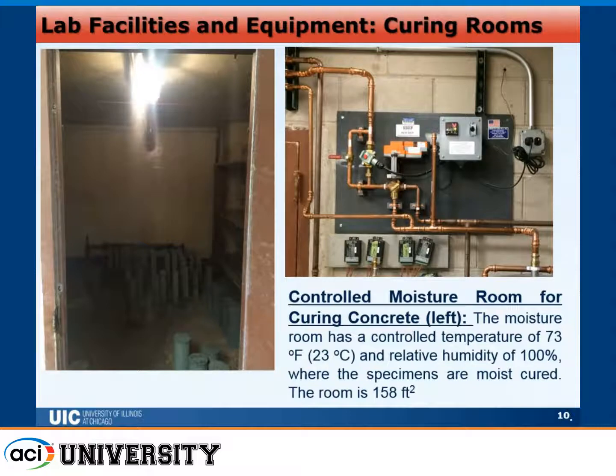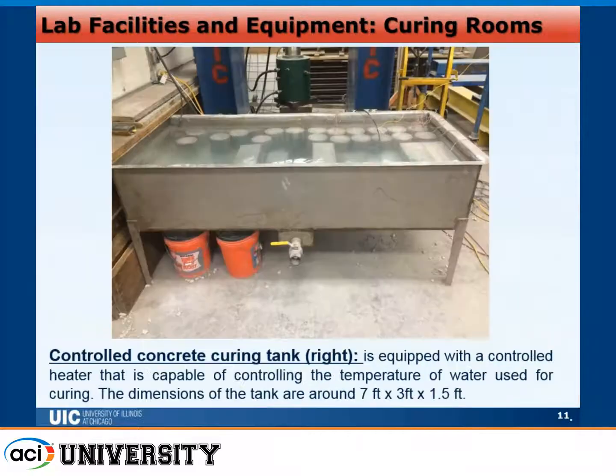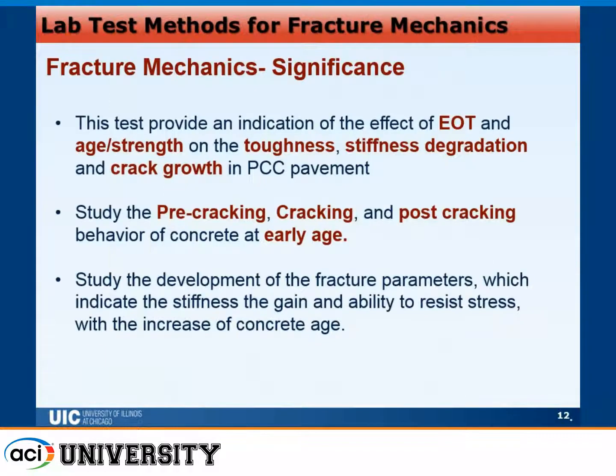This is the moisture room that we used. A special system was applied to maintain a 73 degrees room temperature and a humidity of 100%. Similar thing here, that was a backup, additional way of curing: also a heating tank with full immersion in water.